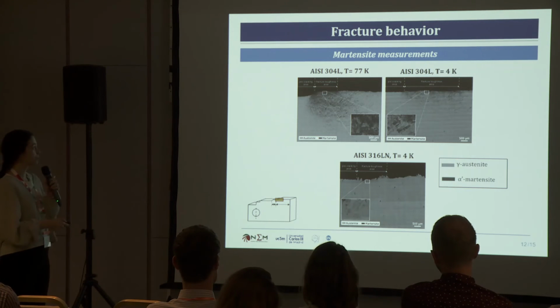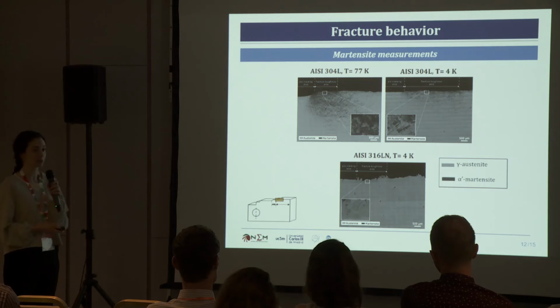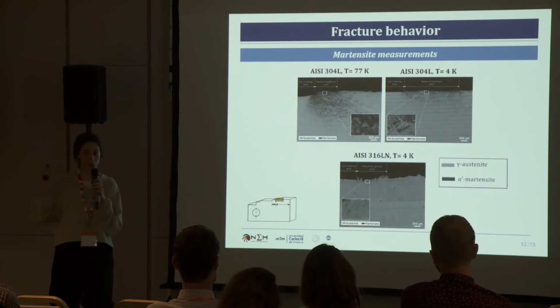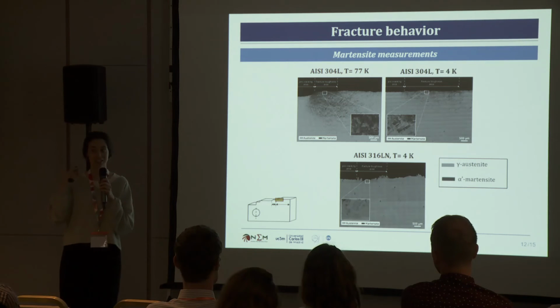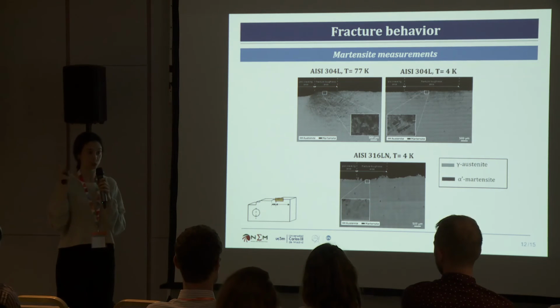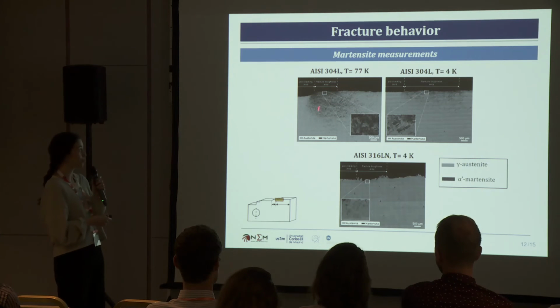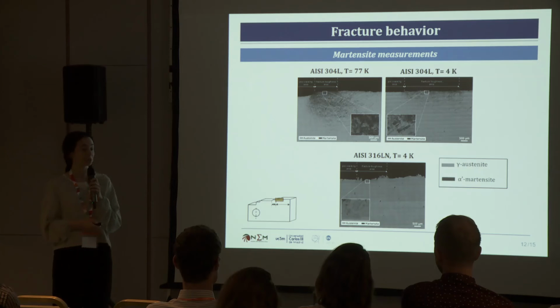Then if we compare for the 304L at 77 and at 4 Kelvin, we see that we have more at 77 Kelvin. And now is when you have to remember what I told you in the past. The evolution of the martensite was quite similar for the 304L at the two temperatures, 77 and 4 Kelvin. So the fact that we have more martensite here than here means that this specimen was submitted to a higher plastic deformation. This is the reason.